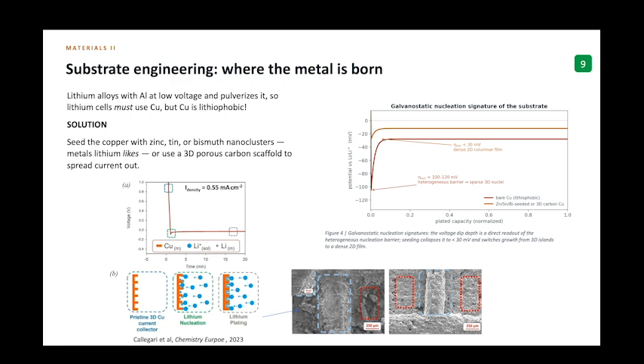But bare copper is lithiophobic. Lithium doesn't want to wet it. See, this voltage curve is really important. The nucleation barrier is deep, 100 to 120 millivolts on bare copper. So it's the sparse islands and filaments that you see. The fix is surface engineering. Seed the copper with zinc, tin, or bismuth, which can avoid the formation of dendrites, as you see in the real SEM images from electron microscopy.